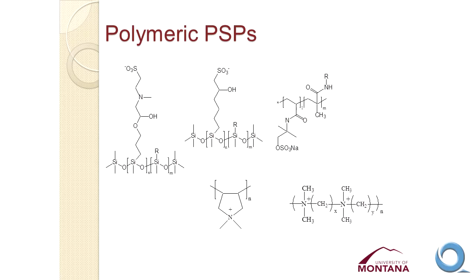The limitation with those materials, though, is that just like SDS micelles, we need to have some sort of a surfactant which will aggregate in solution, and so that limits the range of structures we can study. So we introduced a series of polymers that have ionic groups on the polymer, but then also have sites where we can introduce different chemistry to afford us different separation selectivity.